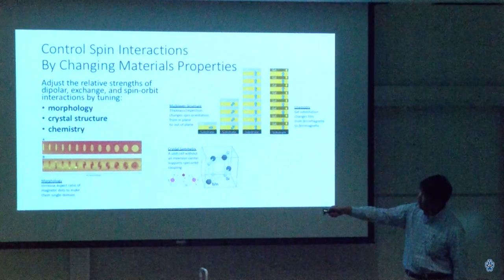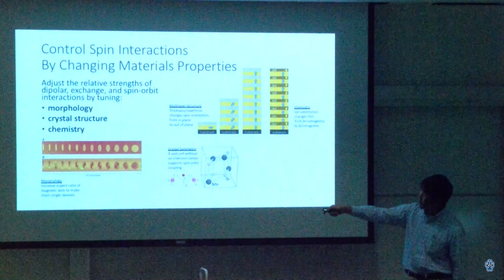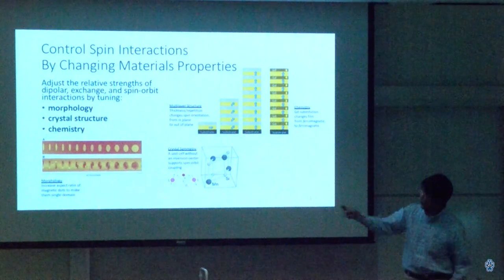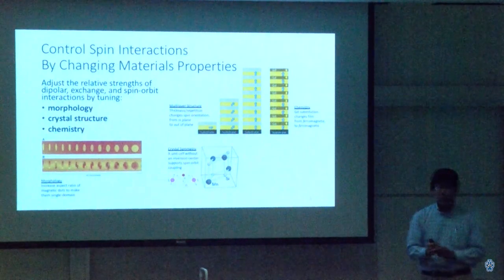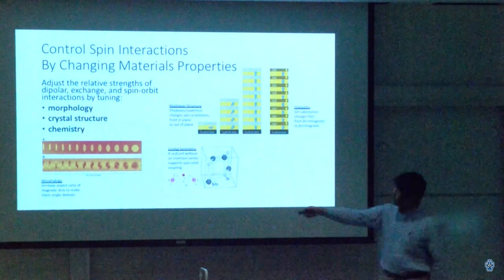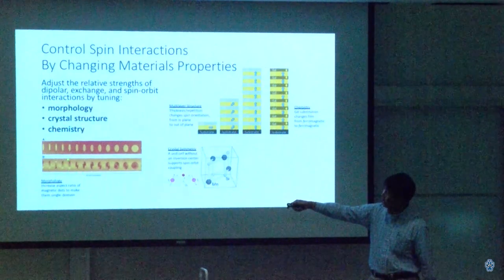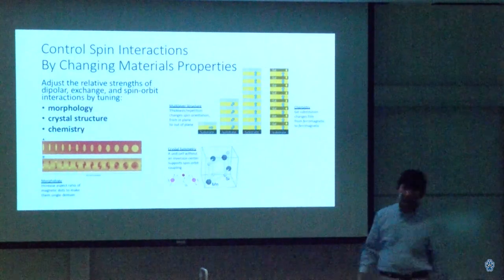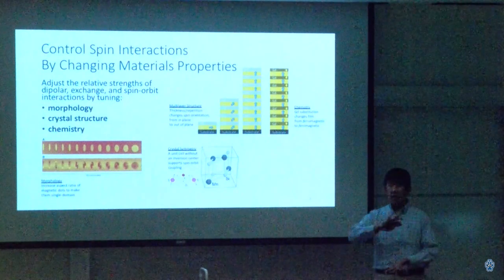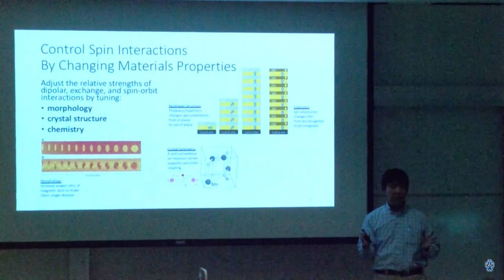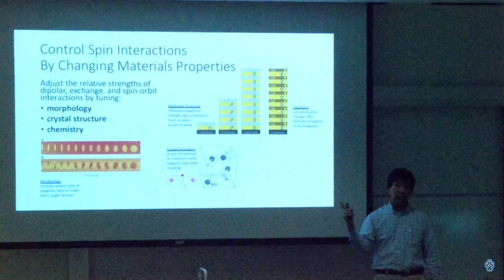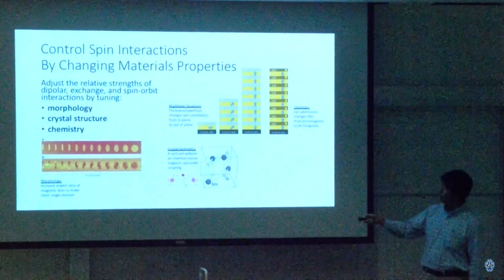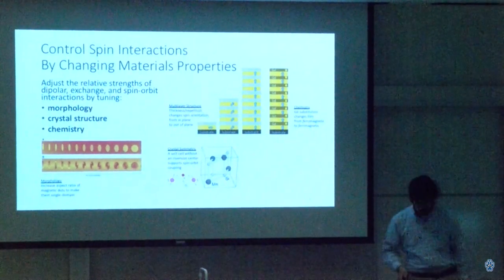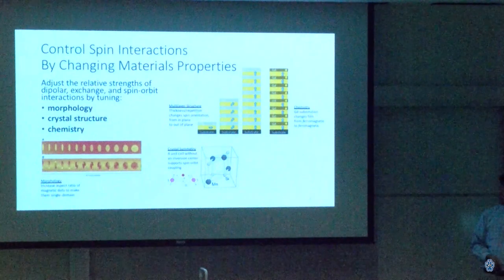This magnetic dot has closure domains, but then you make it a little bit narrower, more candy bar-like, and all of a sudden, it only has one end that is dark and another end that's light. It went from having a closure domain structure to being a bar magnet on the nano scale. Why is that potentially important?